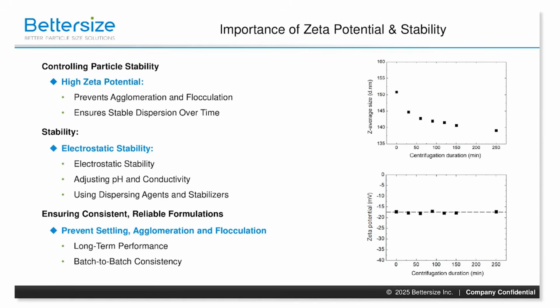Electrostatic stability involves maintaining the forces that keep the particles apart, and this will prevent them from settling at the bottom of the container. By adjusting pH and conductivity, manufacturers can achieve the optimal zeta potential for stable dispersions. Dispersing agents such as surfactants and stabilizers can be added to formulations to improve the electrostatic or steric repulsion between the particles, and this further enhances stability and prevents aggregation.